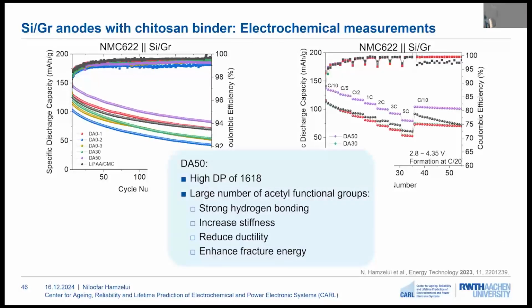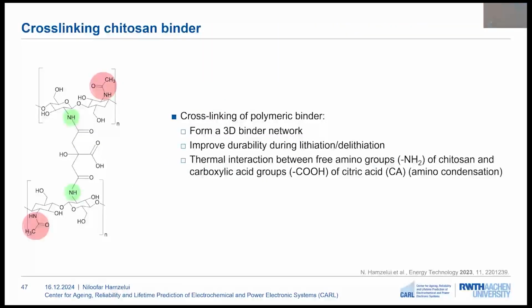So based on the electrochemical measurements, chitosan with degree of acetylation 50 was chosen as the optimized binder to be used in our silicon graphite electrodes. And this can be due to the high number of acetyl functional groups present in this binder, which can form a hydrogen bond with the surface of the silicon and improve the mechanical performance of the electrodes. Then the cross-linking of these binders was investigated using citric acid to form a 3D binder network and also improve the performance of the electrodes upon cycling.